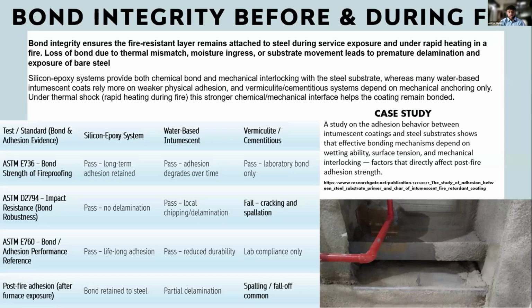Here I have listed a few standards which were tested by us on silicone epoxy, water-based and vermiculite, where we observed that according to ASTM E736, bond strength for fireproofing, silicone epoxy passes with long-term adhesion retained, while water-based also passes with the adhesion degrading over time, and vermiculite also passes that test, but only in the laboratory. Moving on, we'll go with ASTM D2794, an impact resistance test, where silicone epoxy had no delamination, while water-based has local chipping/delamination, and vermiculite coating fails that test on impact.